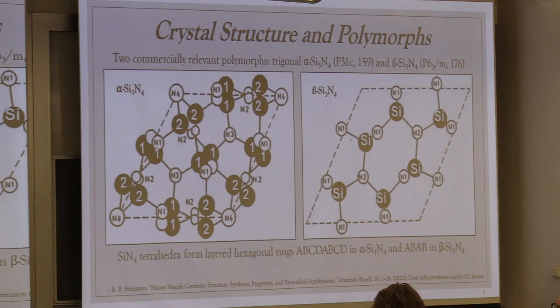One of the interesting things about the beta phase that relates to its microstructure is that the tetrahedra that form the unit cell have a big open space down the middle, a channel. And this channel serves as a diffusion path for ions to move along the c-axis relatively easily. That advances its ability to be sintered, particularly when you add additives. And secondly, it elongates the grains along the c-axis, which gives the microstructure a fibrous nature, which is important for its overall mechanical integrity, which I'll talk about here in a minute too.